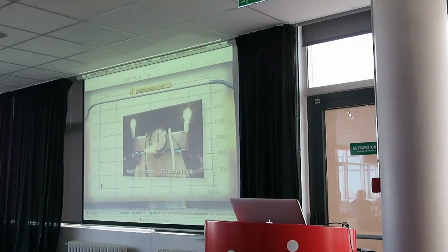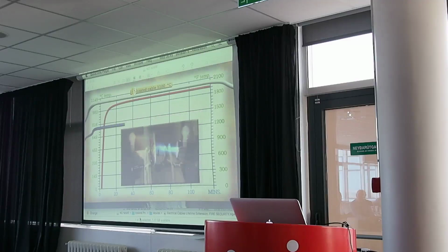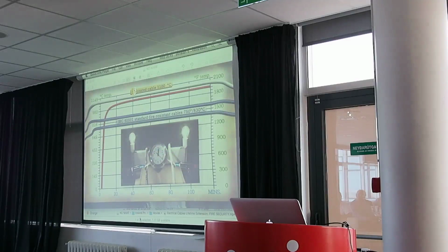FS1 coating system has been tested on an 1100 degrees Celsius oil fire for more than 1 hour without any problem to the insulation or the electrical properties. Normal cables, such as flame retardant and fire resistant cables, cannot withstand such a fire. Our coating systems will guarantee that your cables will function properly under such a fire and be reusable afterwards.